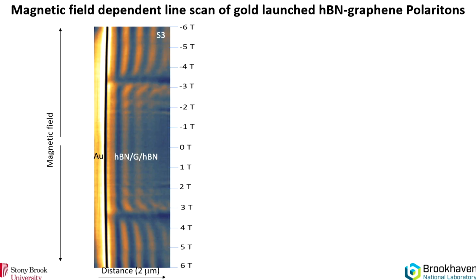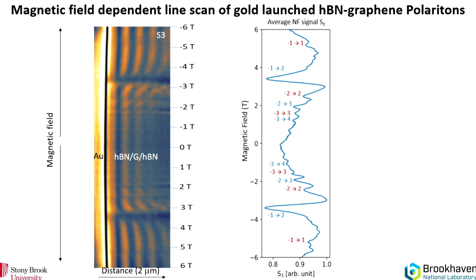And of course, you can do a line scan and at the same time change the magnetic field. This is the line scan at the edge of the gold. And as you change the magnetic field, you can actually see many different Landau levels, including the ones that we saw at 3.3 Tesla. There are actually many others. If you integrate it versus the distance, just to show the magnetic-field-dependent near-field signal, you can see many different orders of Landau level transitions. -1 to 2 is the largest one in this frequency range, and there are a few others.